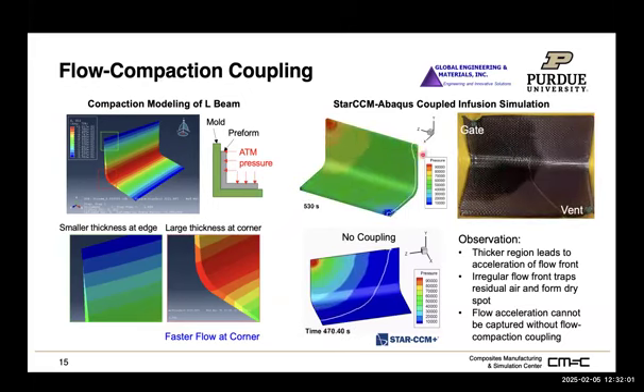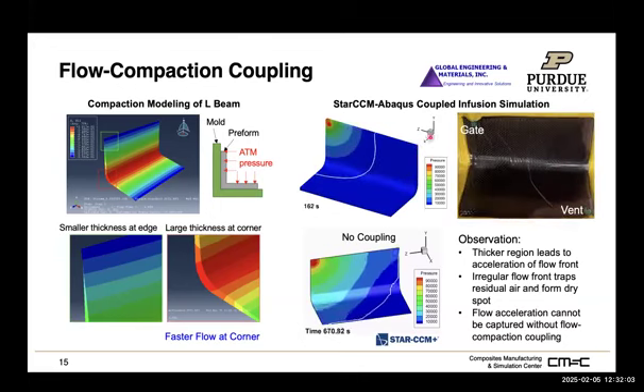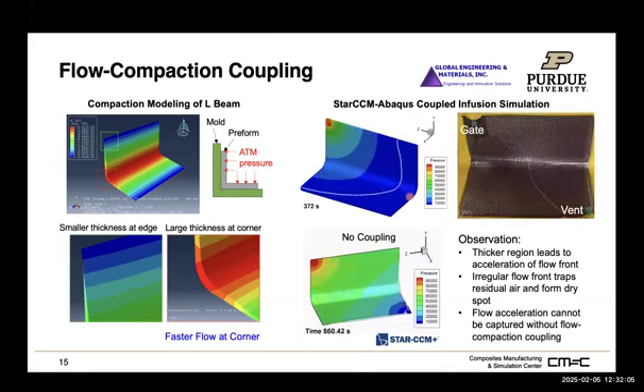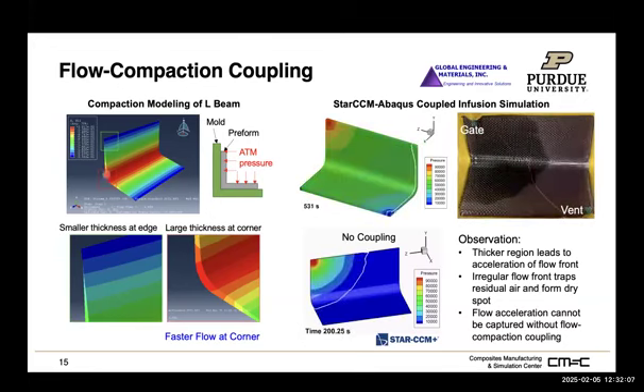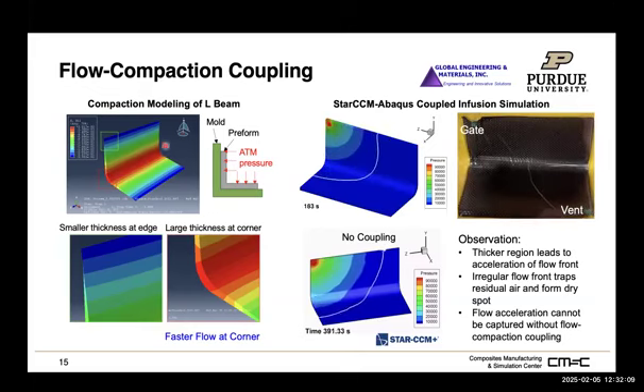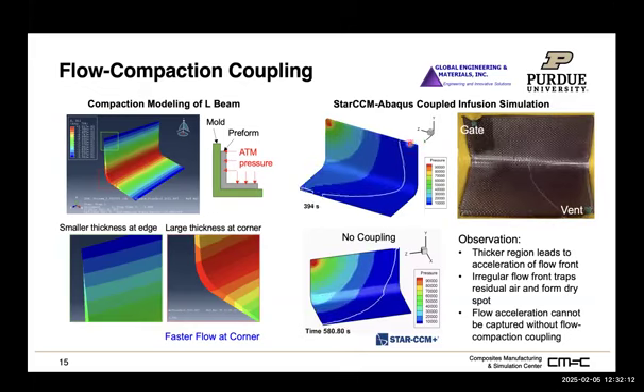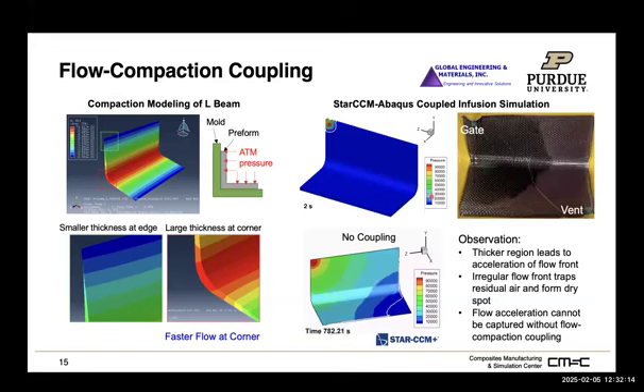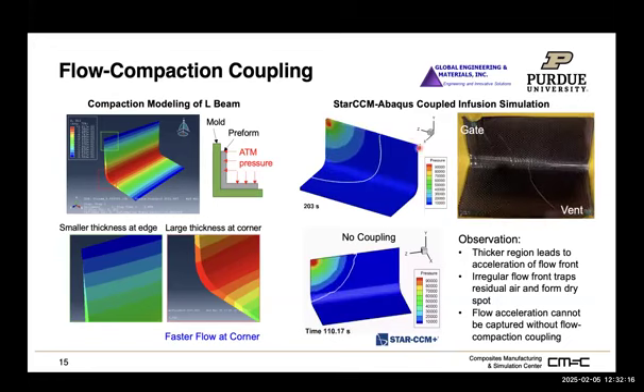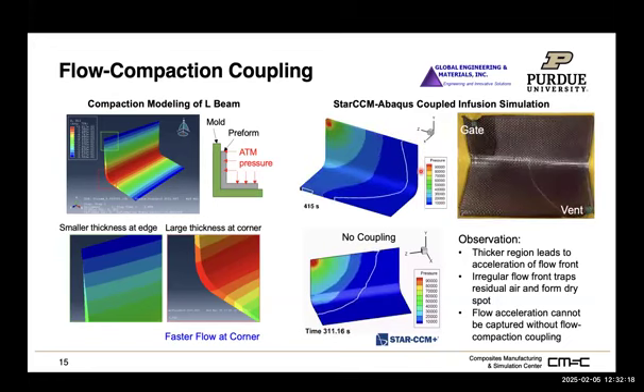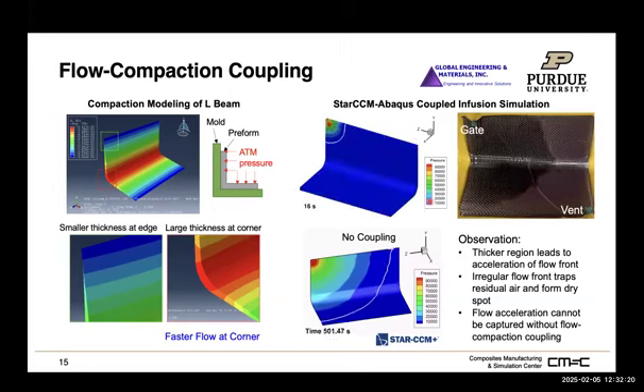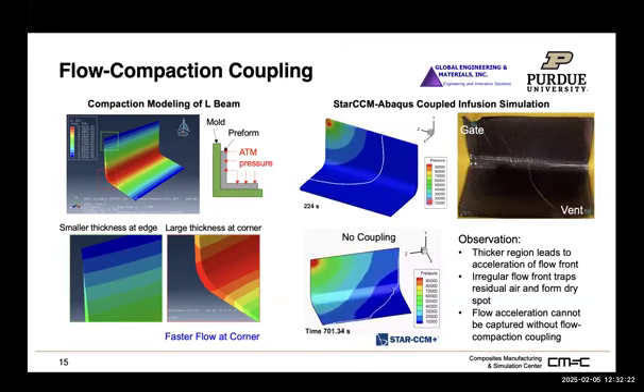And this is also something we observe in the simulation, that if we get accelerated flow because the compaction force is small at the corner, it increases the permeability. The resin gets accelerated, and with those L brackets, it can get a dry spot on one of the flanges.